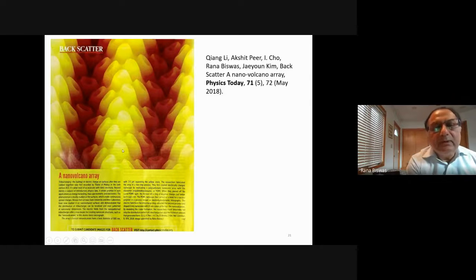But this results, as you can see, in these nanocones, which we call nanovolcanoes. Now, there's a small depression here at the top of the cone, which we call the volcano. And this depression is the indication of the charged ring that resides around the rim of the nanocup. And it is the charge of the ring that gets transferred into the photopolymer. So this is another indirect evidence of the presence of very strong charge in these nanostructures.